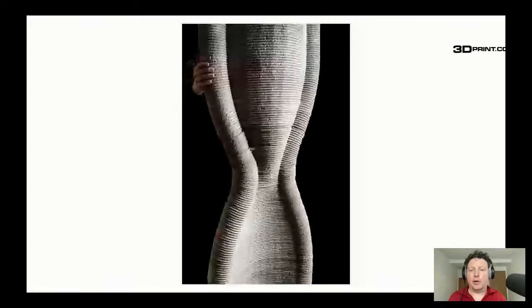So by as much as, in some cases, 72%, by a shell wall method. Essentially what they're doing is using topology optimization to optimize shapes, designing shapes so that the strength is only required at certain locations, and then using non-planar toolpaths and a variable material deposition strategy. What they're doing is essentially just placing concrete tightly where it needs to be.